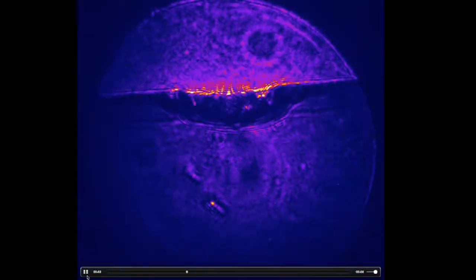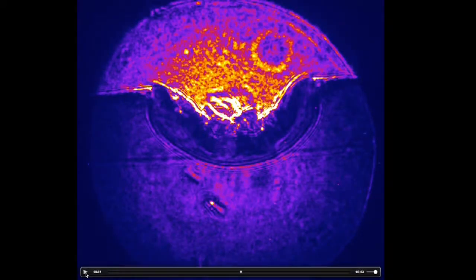So as you see, the shock wave develops. I'll stop it here for a second. It propagates from the center, it pushes the material around, and before the shock wave, you see this very dense region where more of the X-rays have been absorbed. So you can get information about the density of the shock wave you created, obviously the velocity of the shock wave, and you see this other strange feature here, which is actually a linear precursor of the shock. So with this technique, you can image directly on a fairly macroscopic scale what happens when you shoot such a laser. The total field of view here is 300 micron.